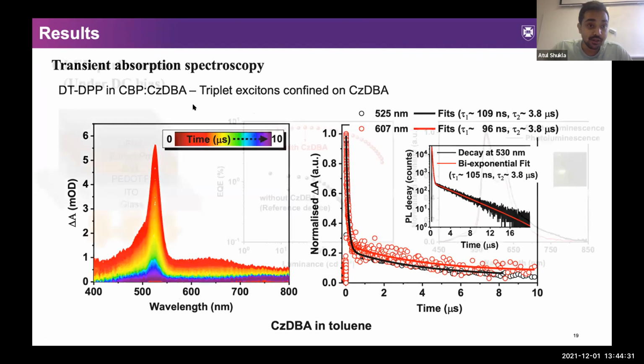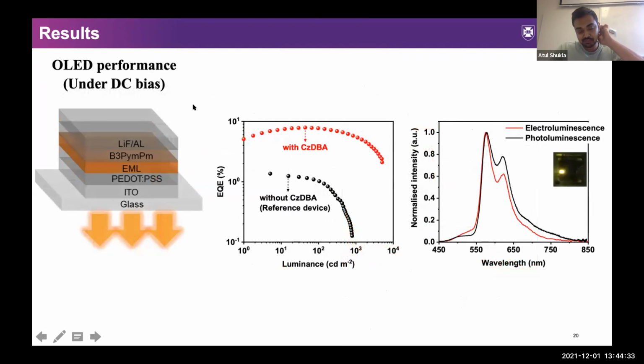So now moving on to devices, we used a very simple, solution-processed device structure. And as you could see in the comparison in this figure, the devices that have 10% doping of CZDBA show significant improvement as compared to just CBP DPP devices. Not only is the peak EQE higher, but the roll-off is also much lower in devices with CZDBA. So this is really good.